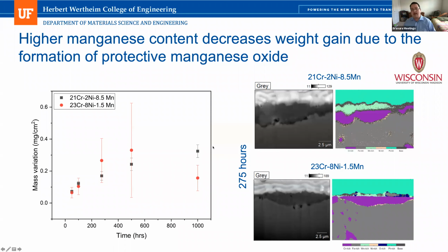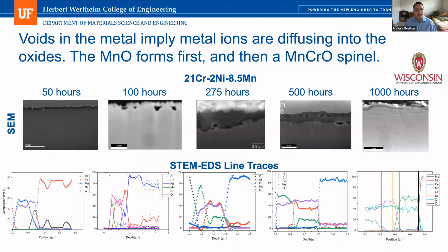Now we can look at EDS results from 275 hours to give us some idea of what's going on here. And what we see is that within the 21-2N, we have a lot more manganese. And so we're getting this manganese oxide layer that's forming, which seems to be more protective, which we don't see in the 23-8N. So the manganese seems to be important. So we're going to look into that in more detail now. So we're just focusing on the 21-2N with the larger manganese now.